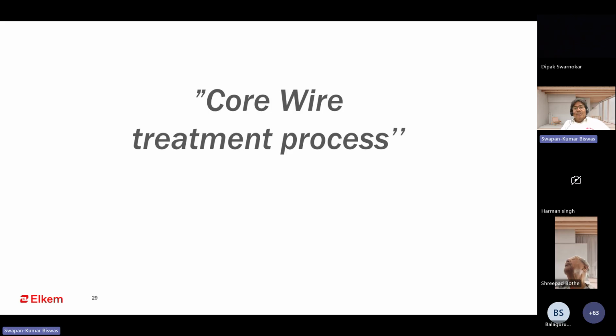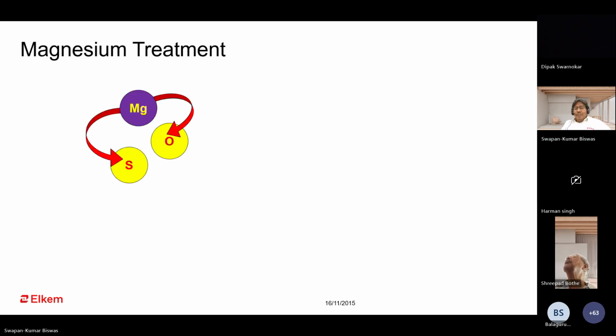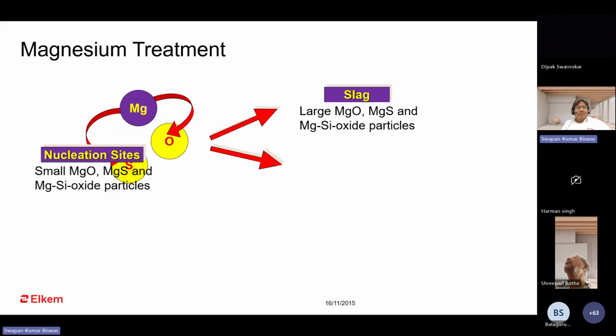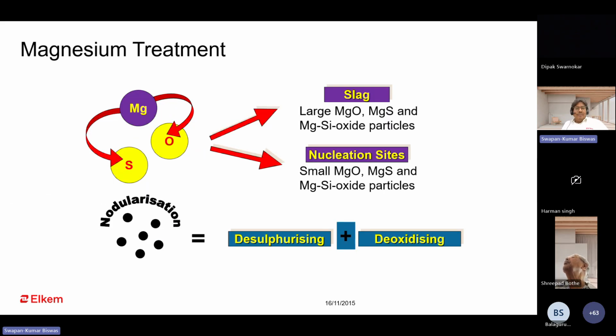So the next topic will be core wire treatment. In any magnesium treatment, normally when we are doing this ferrosilicon magnesium treatment, two effects are going on. This is for the sandwich process. Magnesium, even in core wire, will react with sulfur and also react with oxygen. So the two effects are desulfurization and deoxidation. After this magnesium treatment, there are a lot of MgO, magnesium oxide, sulfide, and magnesium silicon particles. Some will be bigger in size, and those go to the slag. And some are very small, which will create nucleation sites.